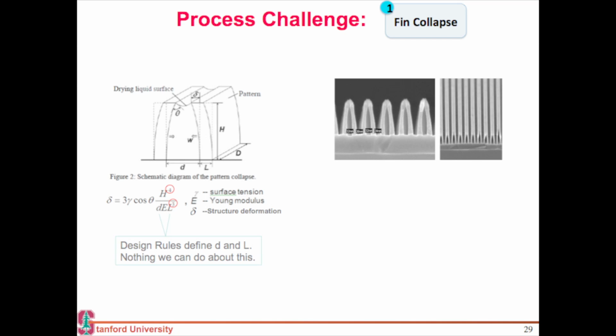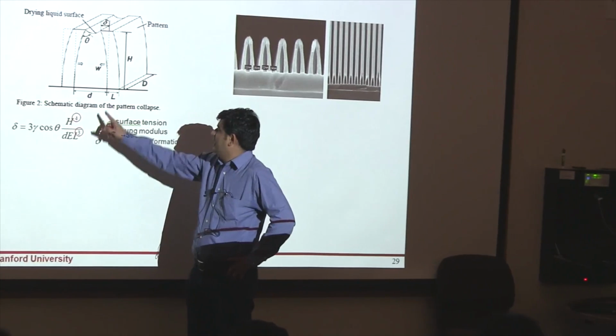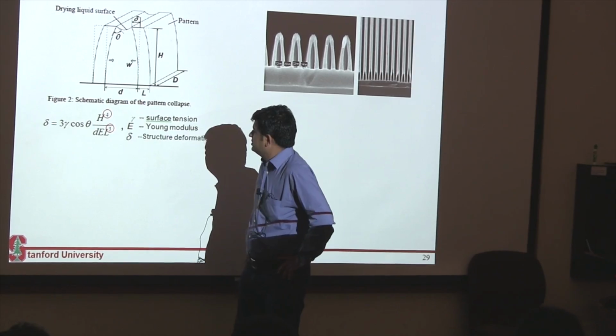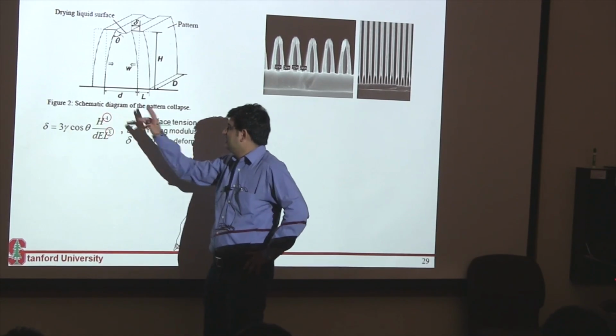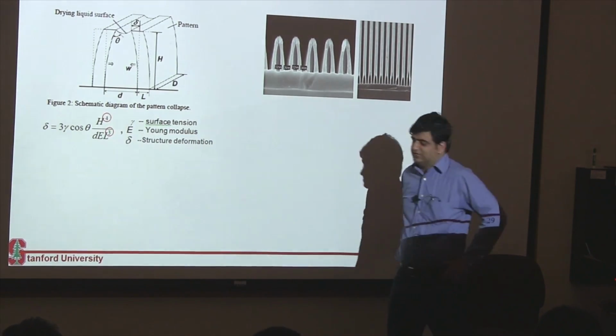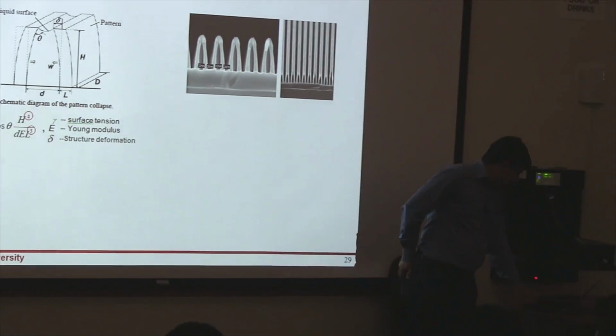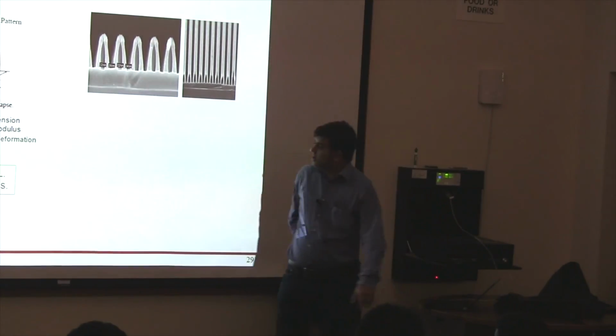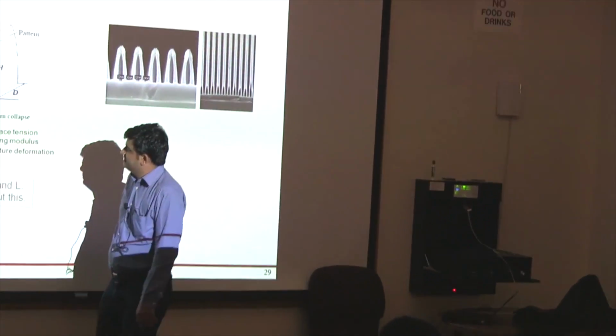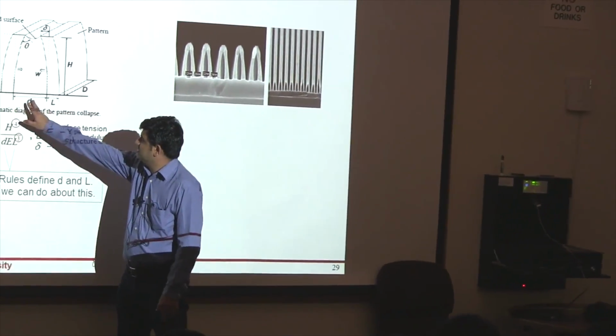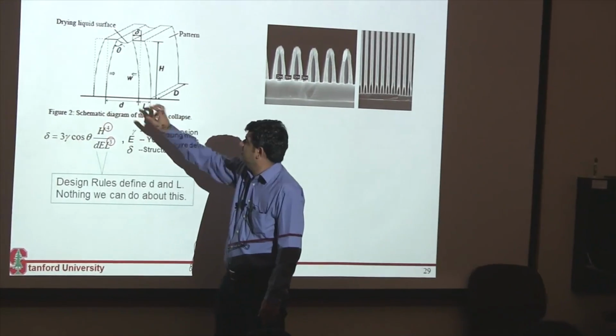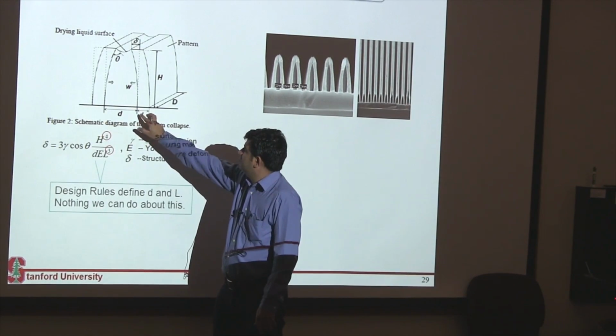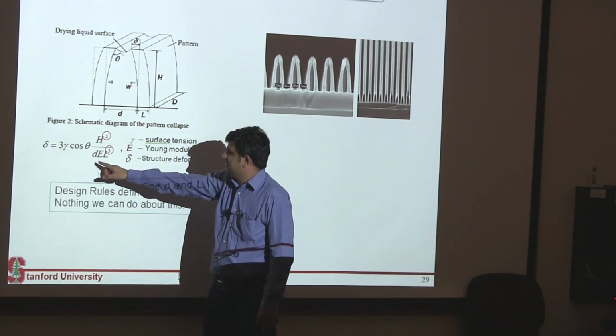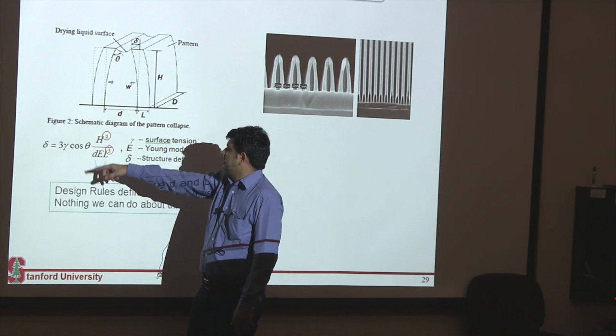It's inversely proportional to the 3rd power of your width, in this case the width of your fin, and it's also inversely proportional to the distance between these fins. A lot of these things are essentially controlled by design rules: how much is the distance between these fins, how thin you can make them. But if you make them thinner, you essentially increase this capillary force.